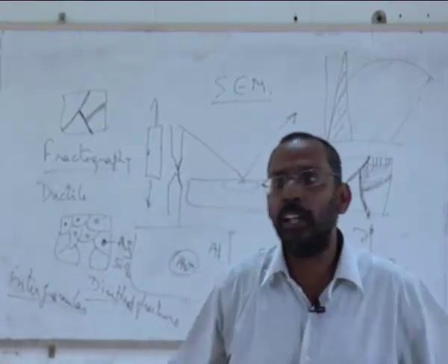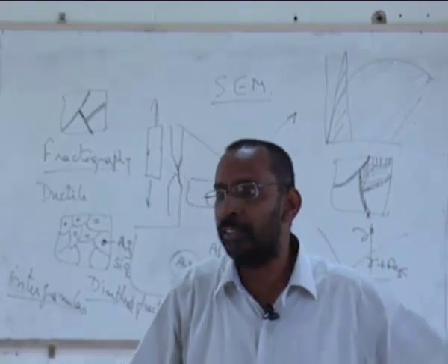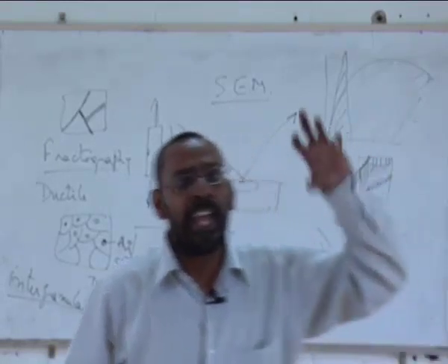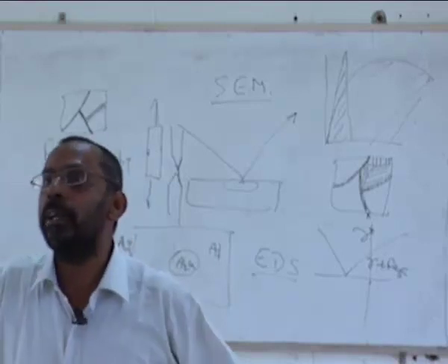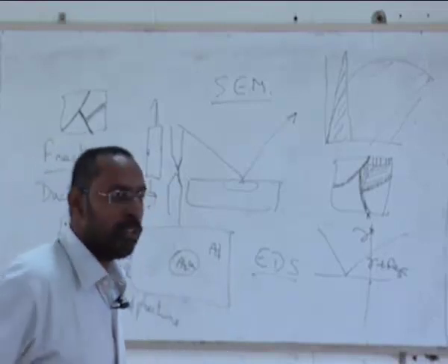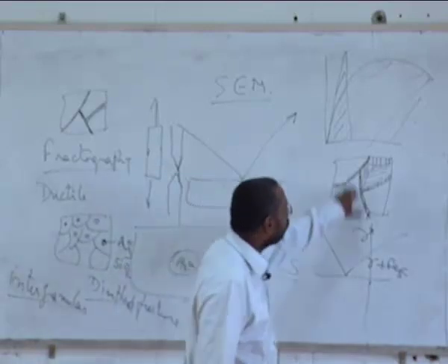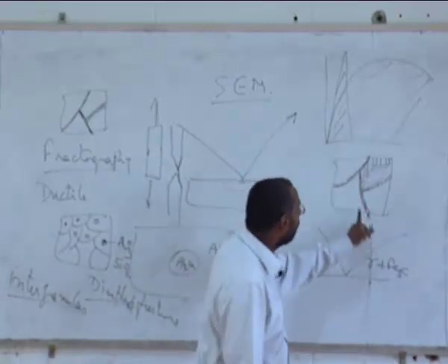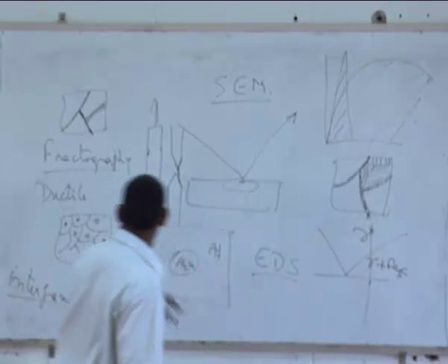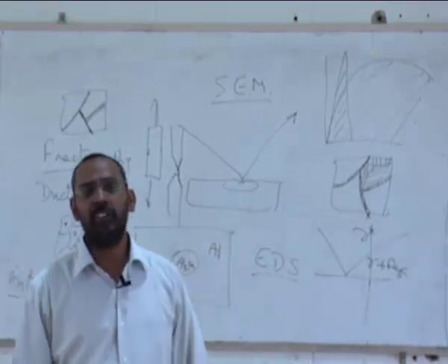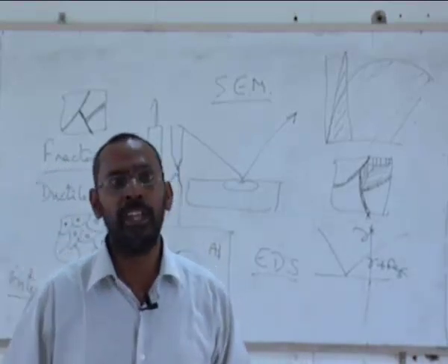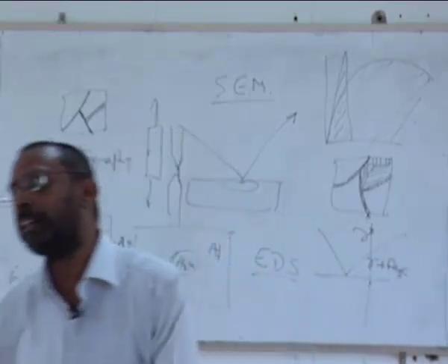That we call toughness, right? Which is nothing but the area under the curve. That area under the curve will be very small for a brittle material many a time. So that is the reason why this material fractures. Because it is fracturing across the grain boundaries, you can call it an intergranular fracture. So by just looking at the fractured surface in an SEM, you will be able to say, yes, this is a brittle material, or a ductile material.